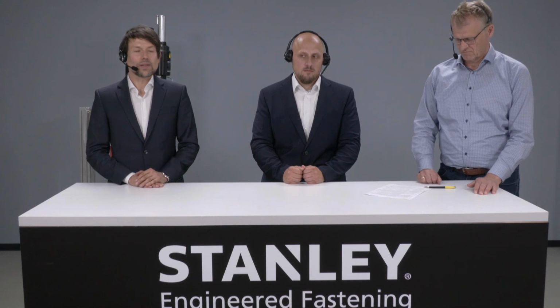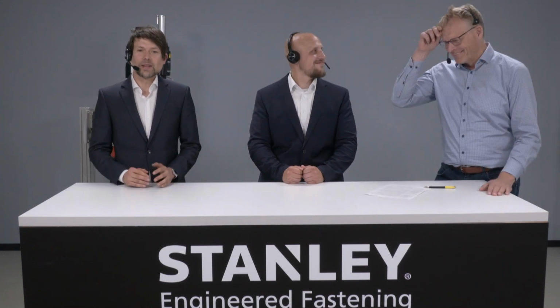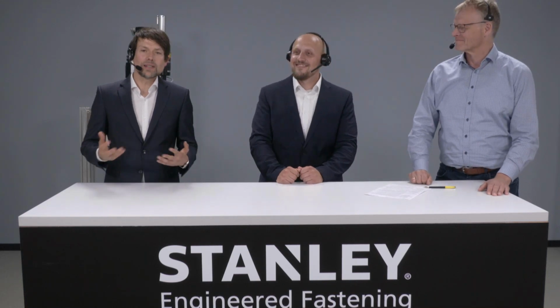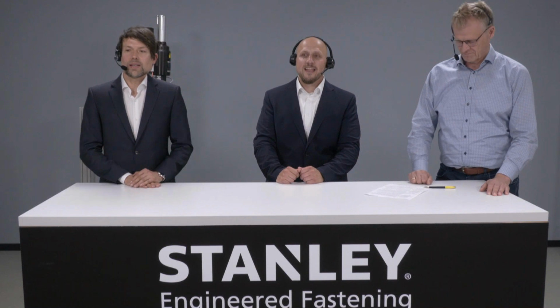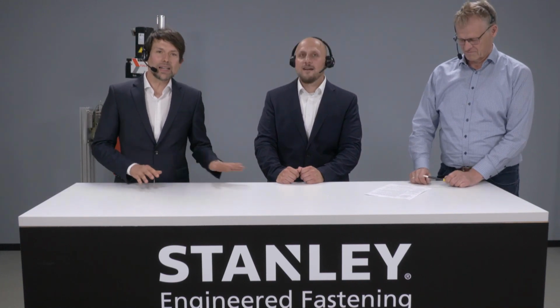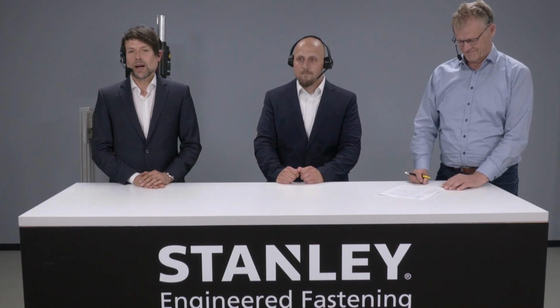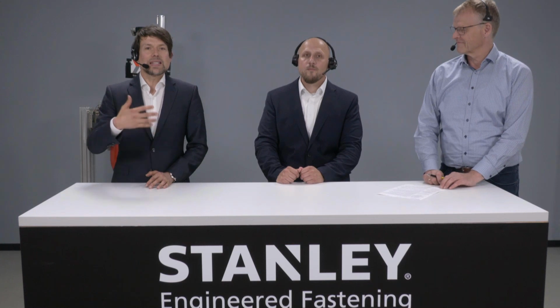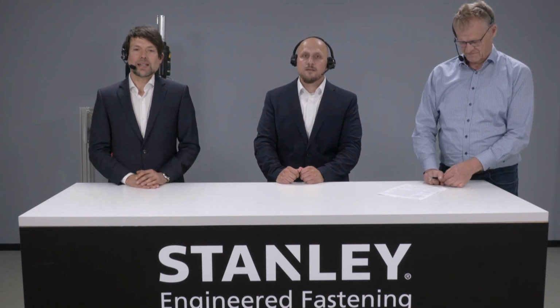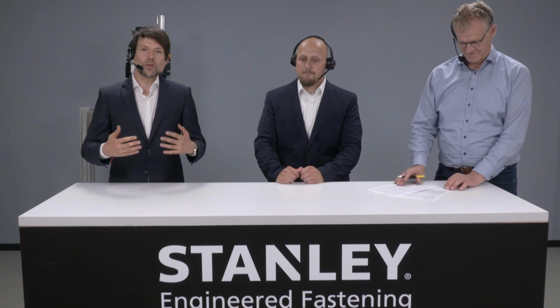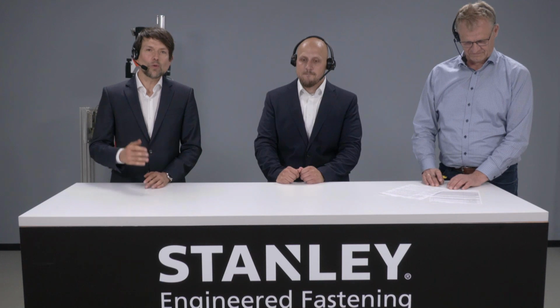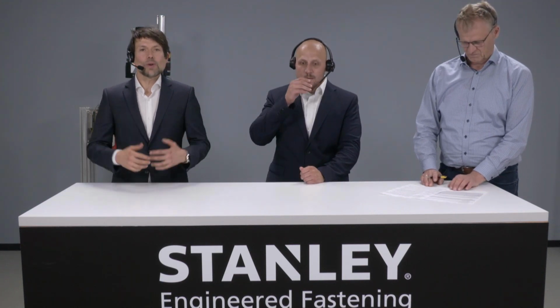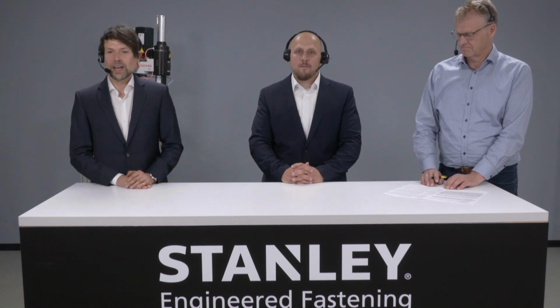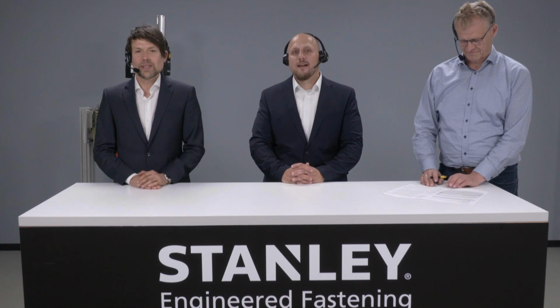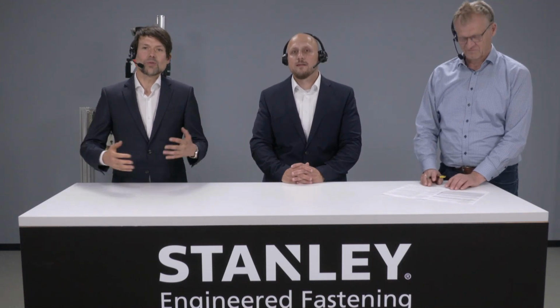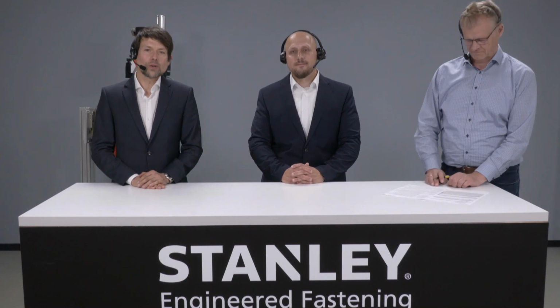Low pressure castings, I think your answer was correct, since the elongation, the ductility, and also the fracture behavior is okay, as long as we use the new rivets and dies Jan just presented. On one of the slides, there was also information about the length of these rivets, because if you have thicker castings due to the production process, you also need longer rivets, and we just increased our portfolio to cover thicker applications where you need longer rivets. And I would like to conclude with the offer: please don't hesitate to contact us. We would like to do some tests for you in order to show you that also with real samples.